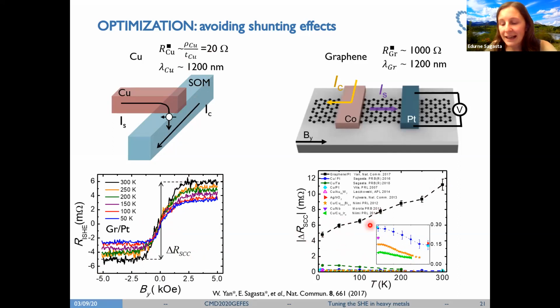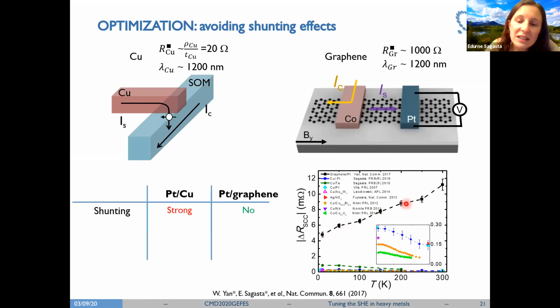So let's clarify where this enhancement is coming from, which is the origin of this enhancement. So first of all, we said that we are overcoming the shunting effect. In platinum graphene, we overcome this shunting effect. So this is one of the reasons we are seeing a big enhancement, but also we are seeing a change in the tendency of the curves with the temperature. And this is due to the spin diffusion length that is telling us how far the electron can transport the spin without losing it. So we see that in case of copper, it decays with the temperature. This is well reported. We know that it decreases with the temperature. So this is the origin of the decaying of the signal.